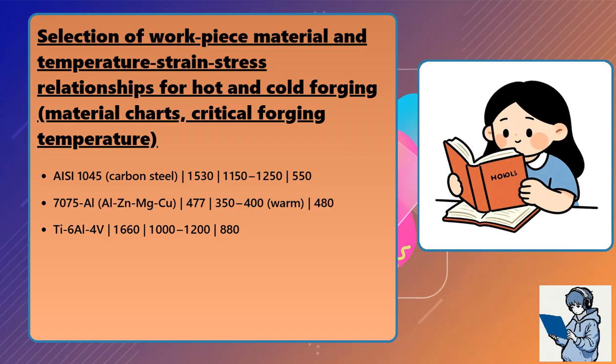Titanium 6 aluminum 4 vanadium, melting point 1660 degrees Celsius. Recommended hot forge temperature 1000 to 1200 degrees Celsius. Typical yield strength cold, 880 megapascals.